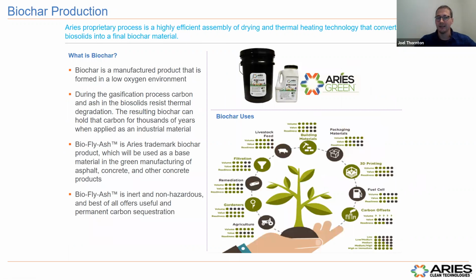So how does that tie into this conversation? As I said, biochar is the byproduct of gasification. It's a mixture of carbon and ash, which resists the thermal degradation in the gasification process. Depending on the feedstock, with woody-based biomass there's a much higher carbon content and much lower ash content, so you get a really high carbon biochar. That material we actually sell on Amazon as a soil amendment, but we have multiple other uses for it. We currently have a supply agreement with a textiles manufacturer that is using it in the manufacturing process of their textiles.